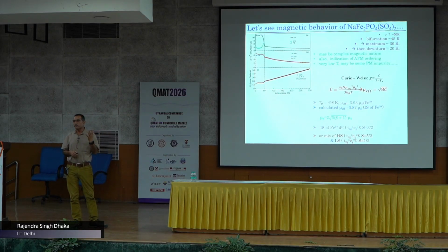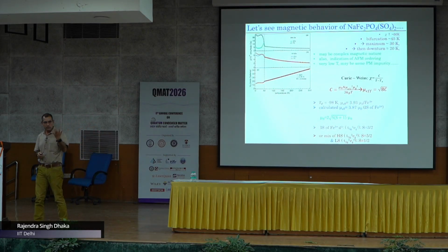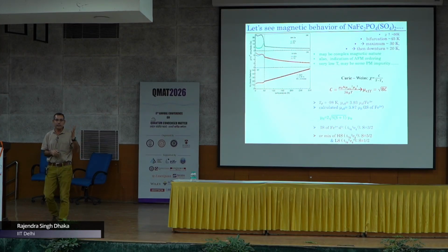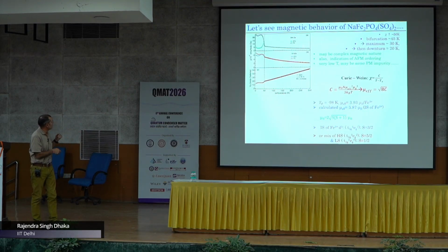Then we were interested in this particular case in the study of magnetic properties. So what we did first is magnetization versus temperature, and you can see in these 2 panels the M-T curves taken at 2 different fields. One of them is at 500 Oe, and in M-T what we have to do is zero field cooled and field cooled.